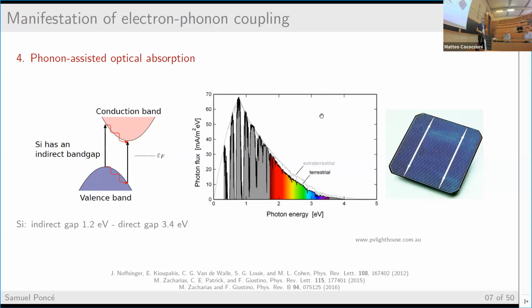In contrast, if you have direct band gap materials, then you're also able to absorb light, but using much thinner materials. And this is the excitement around perovskite, for example. Perovskites usually have a direct band gap, and this allows you to have a very thin material for absorption.